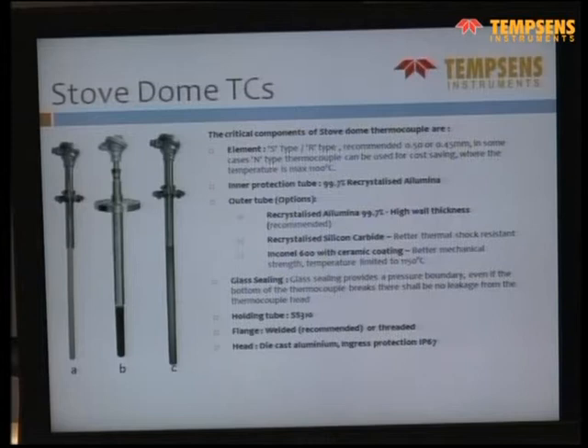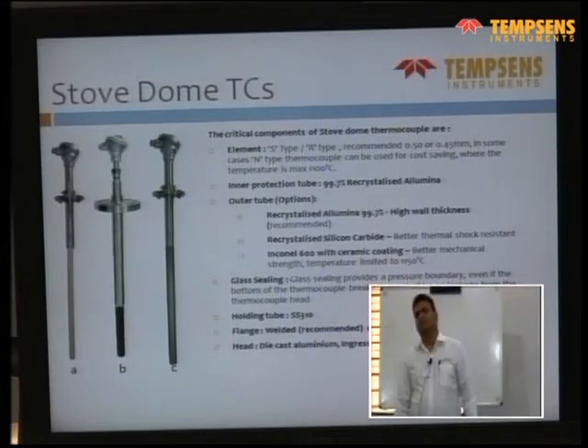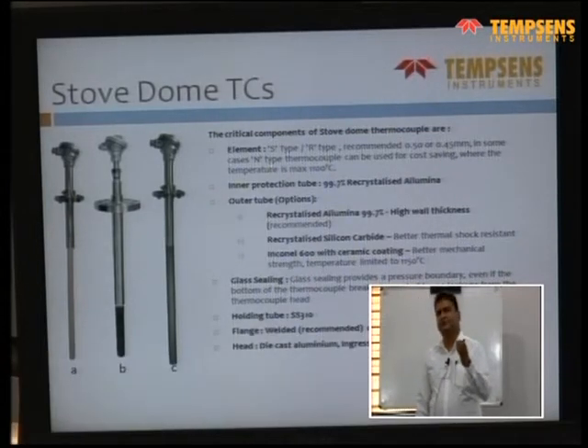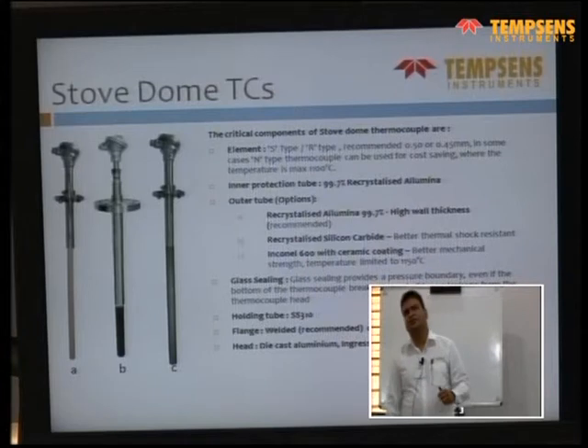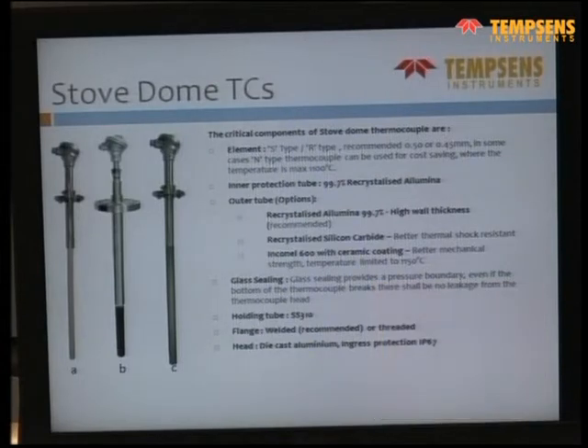So we have this application in which there are three solutions. The first one is with double ceramic protection. Inside is an S-type or R-type thermocouple, and there are two layers of ceramic, and outside the holding tube. The second solution has silicon carbide outside and ceramic alumina insulation inside, and the third one has inconel outer and inside is again alumina. As I told you earlier, for all R-type, S-type or B-type thermocouples, you need to have a layer of ceramic so that it is protected from the outside environment.